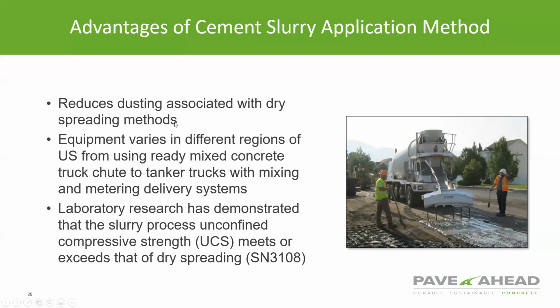So this would come into play in an urban setting, or perhaps you're next to a hospital or other facility where you really don't want any dusting. That would be an ideal place to use a slurry method. Also in, let's say, a cul-de-sac or very tight quarters, the ready mix truck can bring that slurry in those very tight places with ease. There is a variety of equipment available for delivering that slurry using a ready mix truck, and there's also tanker trucks as well that can deliver slurries.